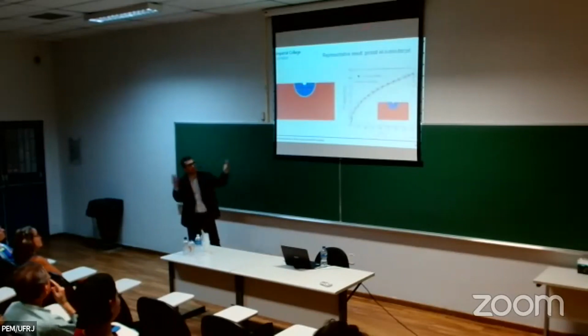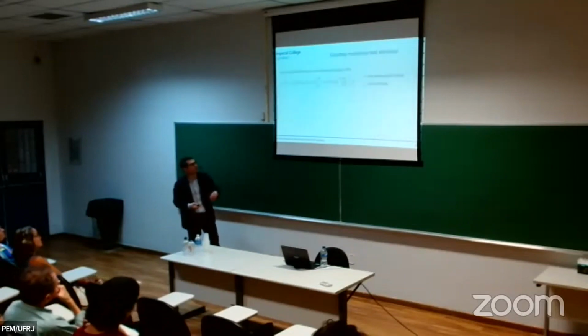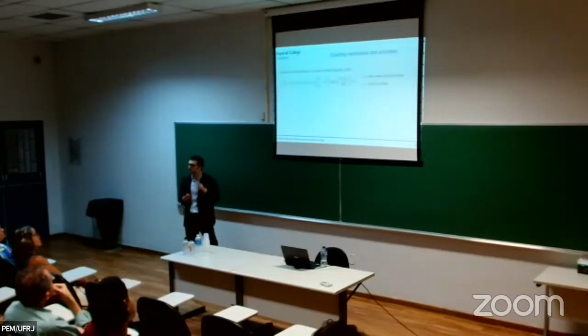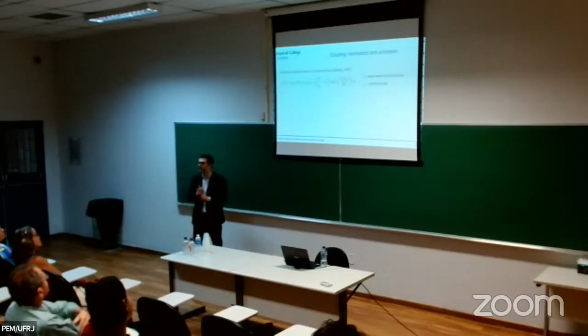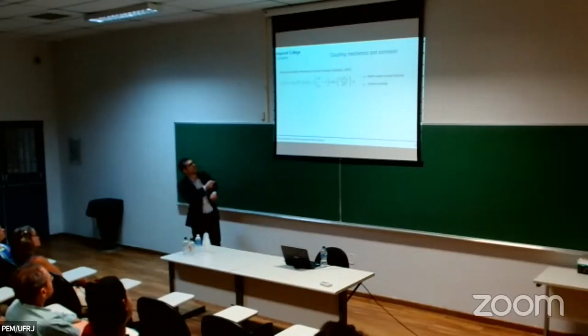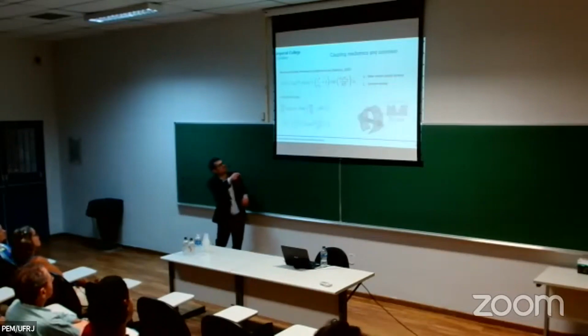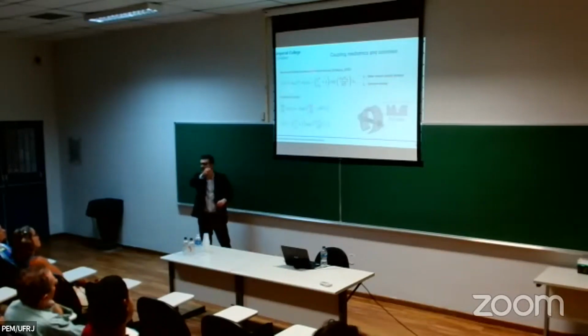But anyway, we can predict not only 1D, of course, but also 2D cases compared with other calculations. And we have also introduced two mechanical elements that I think are important. The first one is the fact that we know that mechanical fields enhance corrosion kinetics. We know this from the work by Gutman. This is the corrosion rate, and you can see that it depends on the plastic strains and the hydrostatic stress. So we can incorporate that into our model because you can make this phase field mobility coefficient, which you can relate quantitatively with the corrosion current density, dependent on these mechanical fields.